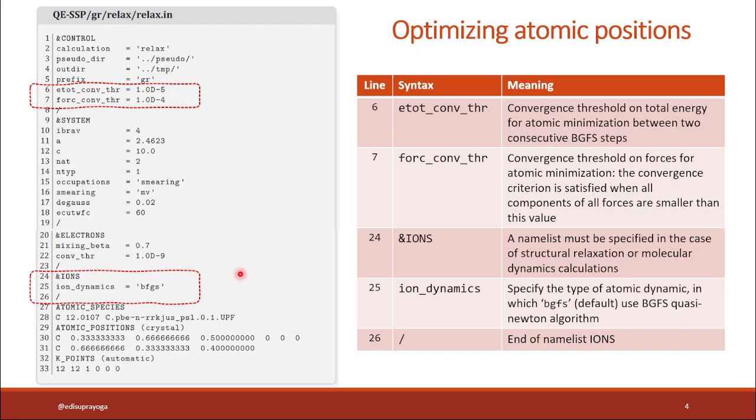And here is the description of some input variables. In order to observe the displacement of a carbon atom in a unit cell of graphene, one carbon atom is fixed by adding 3 0s here, and the other carbon atom is set to be relaxed. We expect that this atom position will move to the optimal position.